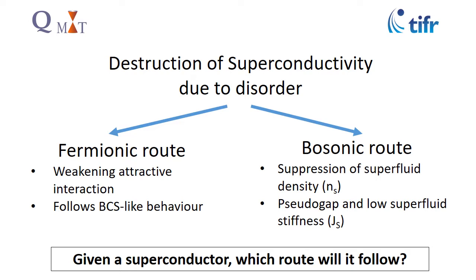There are in general two routes. First is called the fermionic route, where the attractive interaction, which is responsible for the superconducting Cooper pairs, gets weakened due to disorder scattering. On the other hand, in the bosonic route, the superfluid density itself gets suppressed due to disorder. For the fermionic mechanism, the parameters more or less follow the conventional Bardeen-Cooper-Schrieffer theory, while for the bosonic they don't. And for the bosonic mechanism, the superconductor is more susceptible to phase fluctuations.